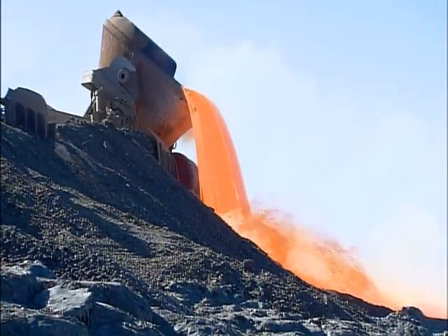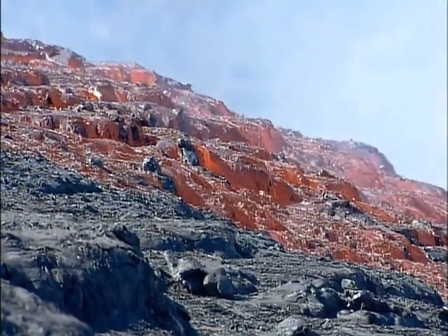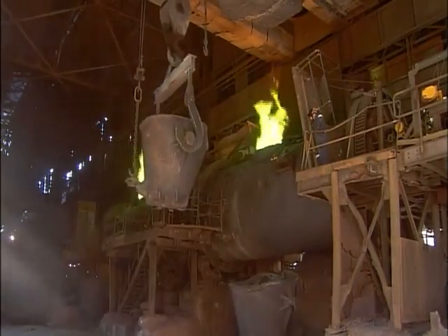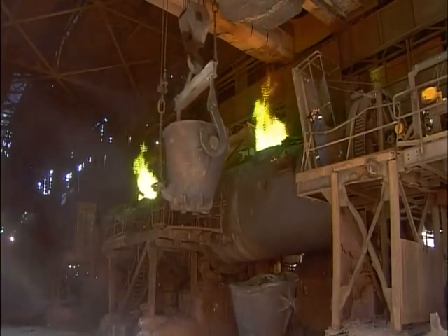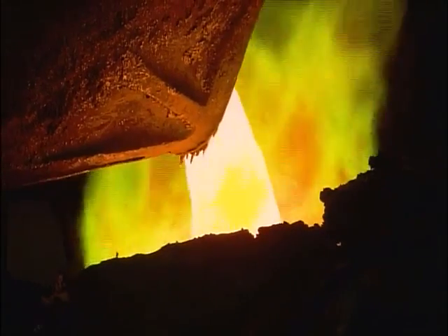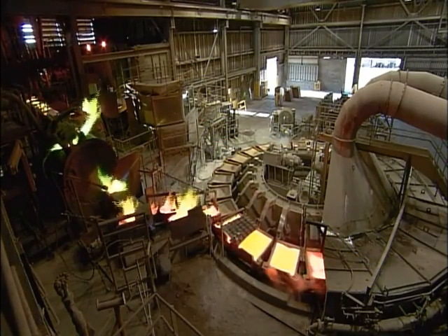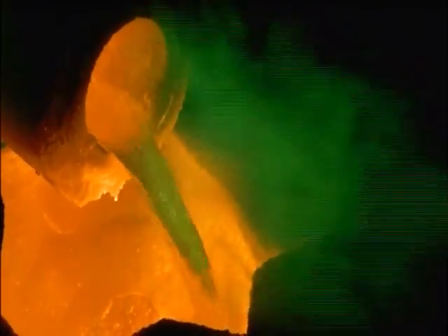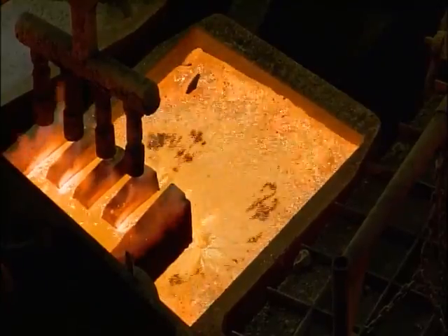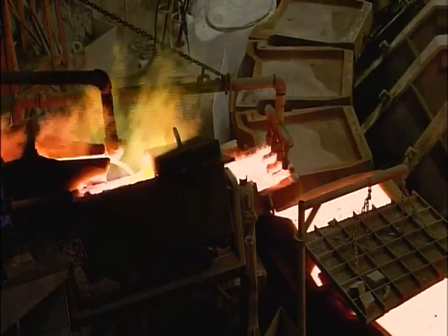With the copper now extracted from the ore, they pour the residue onto a heap. This molten slag flows down like lava from a volcano. As it cools, it becomes part of the landscape. Meanwhile, in the smelter, a crane delivers the fiery liquid copper into another furnace for further purification. Inside this furnace, the purity level increases from 98 percent to 99.4 percent. The molten copper flows out of the furnace and into rotating molds. The molds shape the copper into big rectangular slabs called anodes, which will serve as positively charged electrodes in the electro-refining process still to come.